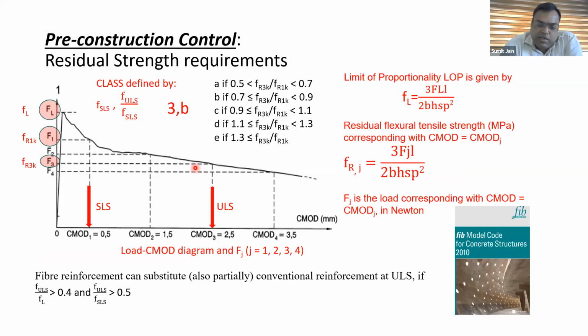Under the 3-point bending test, we are defining the class of shotcrete by a simple number and an alphabet. The number is the SLS residual stress which is required by the designer, and the letter categorizes the ratio of the ULS residual stress versus the SLS residual stress. These numbers are coming from the fib Model Code. The fib Model Code is a well accepted code. You can see an image of the code on the bottom right of the slide.